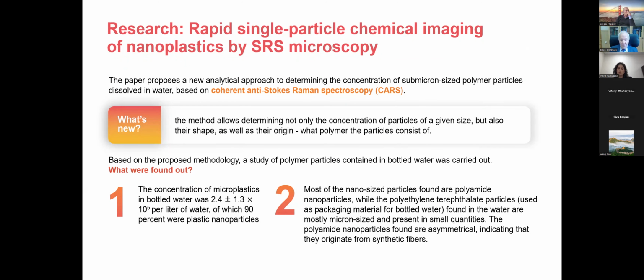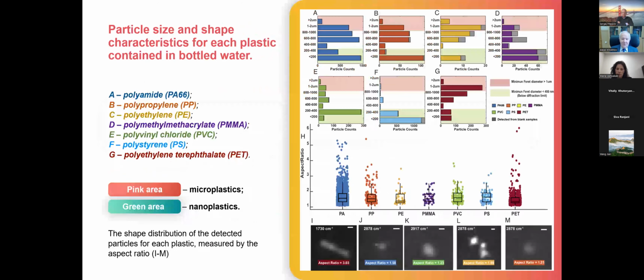This is, of course, a very big amount, but on the other hand, this is in the nano range. So the smaller the particles, the larger the number of particles per unit volume. And it was discovered that most of these nano-sized particles are not polyethylene terephthalate particles from which the bottles are made, but polyamide nanoparticles. Here are the corresponding graphs, and you see that polyamide nanoparticles, in the blue range, are more than 1,000 particles, and polyethylene terephthalate is much smaller, less than 10 particles. So it's 2 orders of magnitude.